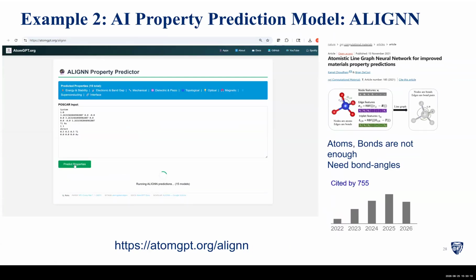Now, once you have these data sets, what you can do is make a graph neural network model. As I said previously, computers do not know physics, chemistry, materials. They only know numbers. So one of the ways to convert atomic structure to numbers is, suppose you consider this SiO4 tetrahedra. Silicon is the blue atom, red is the oxygen atom. One way to distinguish silicon from oxygen is based on atomic number, atomic mass, and so on. These are node features. The edge features are the atomic bonds, which are a sort of radial basis function based description. Now, this was fine until 2018, 2019, but they did not consider bond angles at that time.